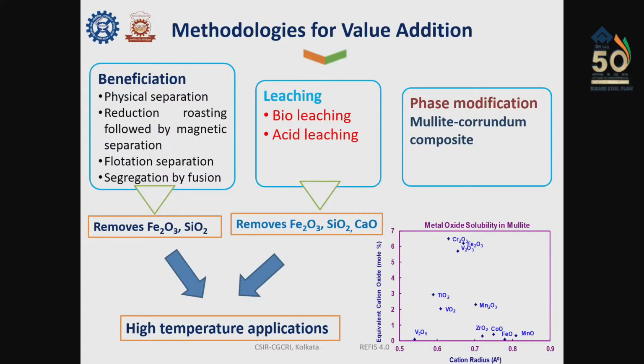And the third option is basically phase modification. If we can control the low melting phase formation by changing the phase assemblage or by tailoring the phase formation, then we can improve the properties. CSIR-CGCRI works mainly in this area. If you see this solubility diagram at the bottom corner, iron oxide and TiO2, the two impurities present in bauxite, have a good amount of solubility in mullite. Mullite is basically a solid solution. So if we can convert to mullite before the formation of the low melting phase, we can restrict the low melting phase formation and thereby enhance the properties.